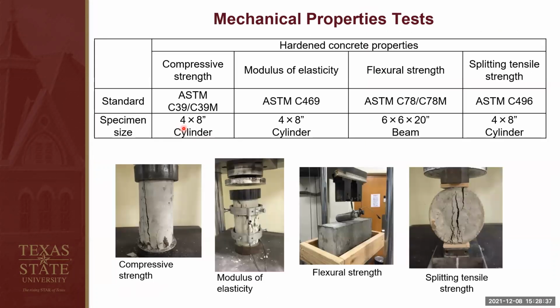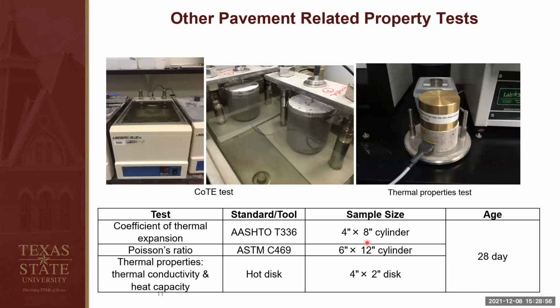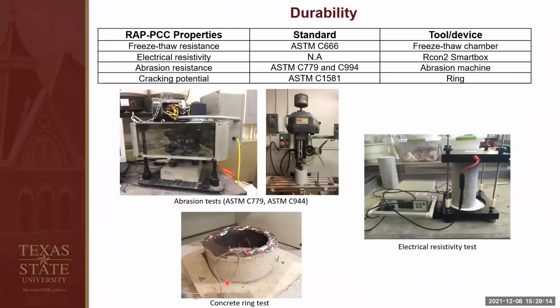Then we also did a lot of conventional mechanical tests based on the ASTM standards. We did compressive strength, modulus of elasticity, flexural strength, and we also did split tensile strength. And here are some pictures showing the tests. And we also did some pavement related property tests, including coefficient of thermal expansion, Poisson's ratio, and we also evaluated the thermal properties, including the thermal conductivity and the heat capacity of the RAP concrete.